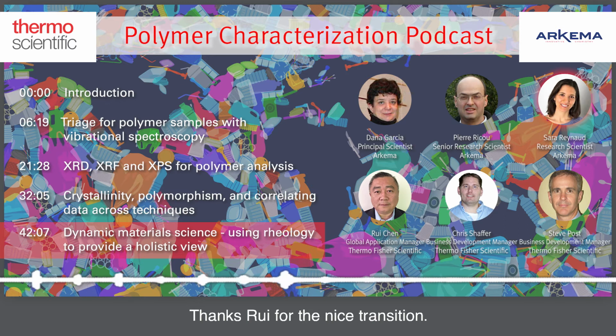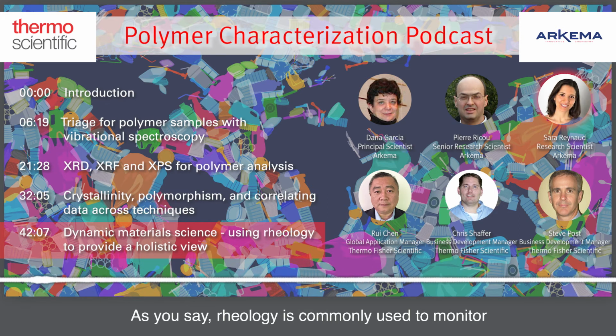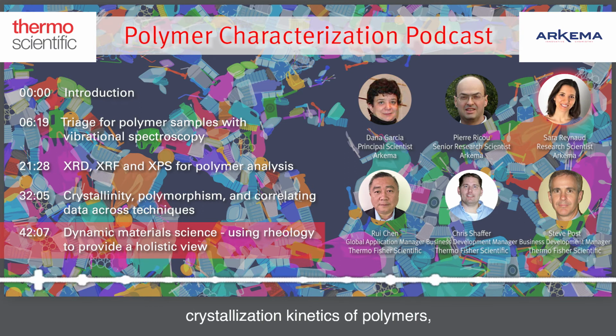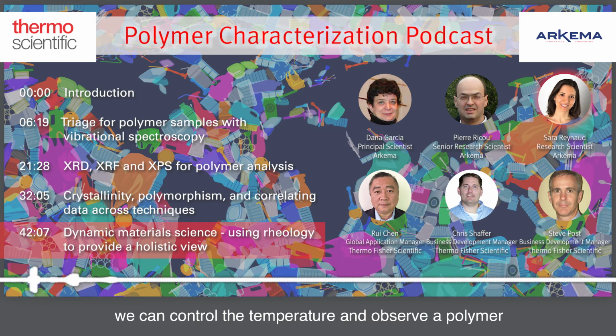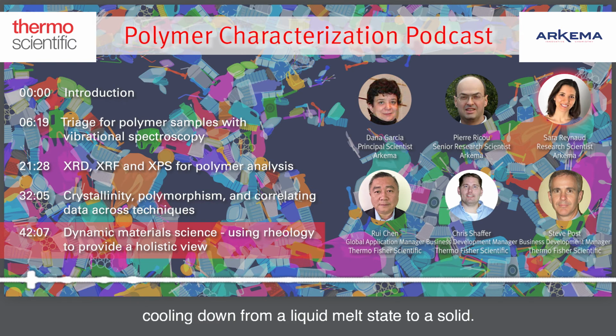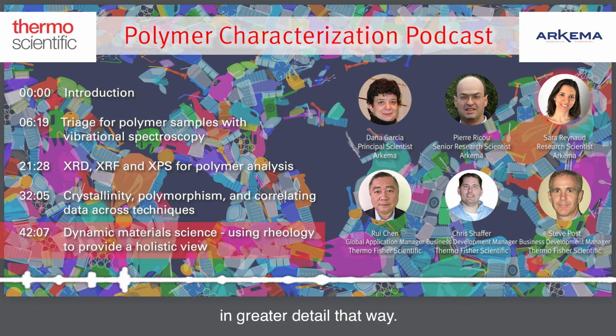Yeah, thanks, Rui, for the nice transition. As you say, rheology is commonly used to monitor crystallization kinetics of polymers, particularly semi-crystalline polymers. That's quite obvious since we can control the temperature and observe a polymer cooling down from a liquid melt state to a solid. Even more, we can apply shear and strain to mimic the real processing conditions, so we can monitor the material response in greater detail that way.